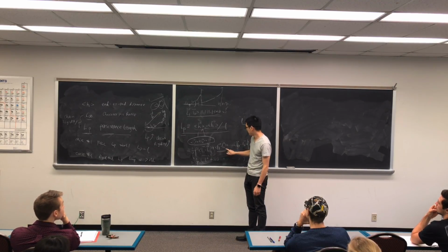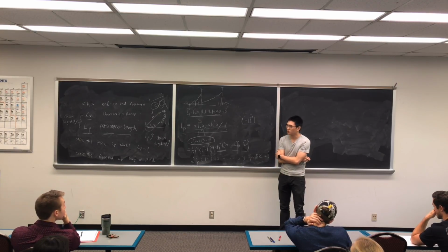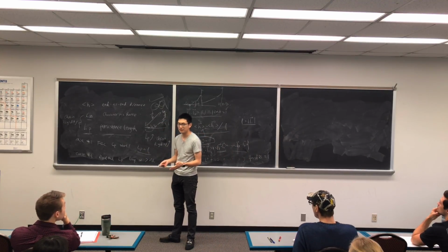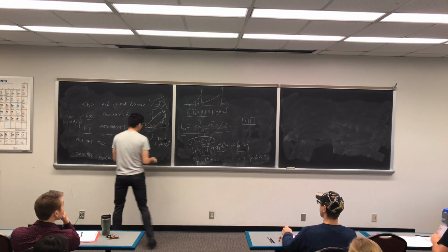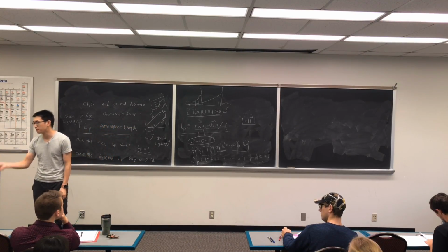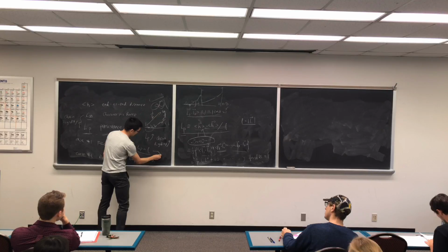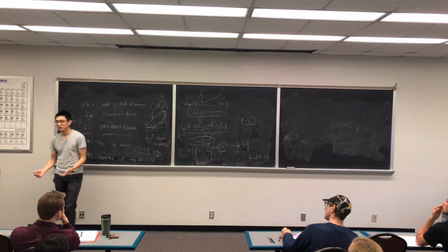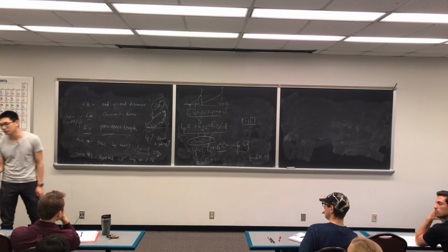And for free rotation chain, everything else is basically going to be 0. And that's for free rotation chain. You will see the persistence length is just itself by one single bond. And physically, you can understand, as I said, the persistence length is how long it takes your chains to bend 90 degrees. If you have a free rotation chain, right? So the second bond can immediately bend 90 degrees or even further, so it will lose persistence at first bond angle. That's why persistence length will be equal to L.